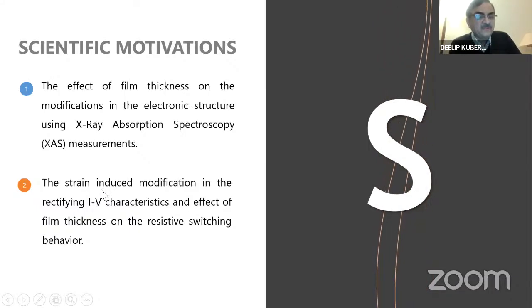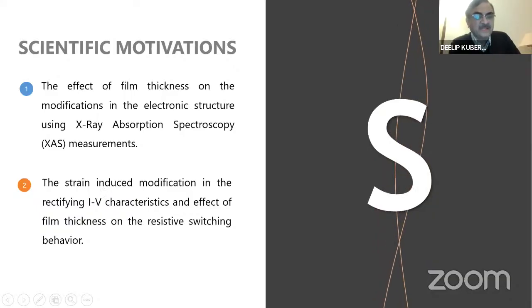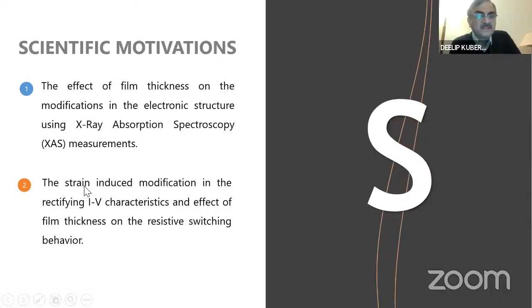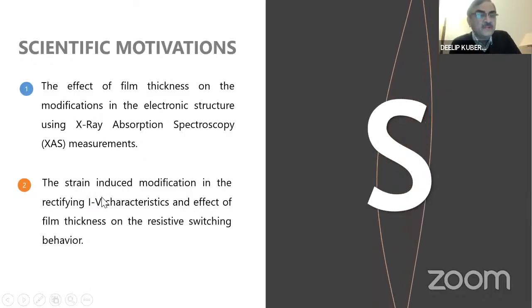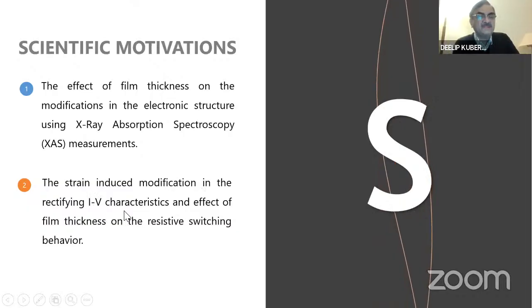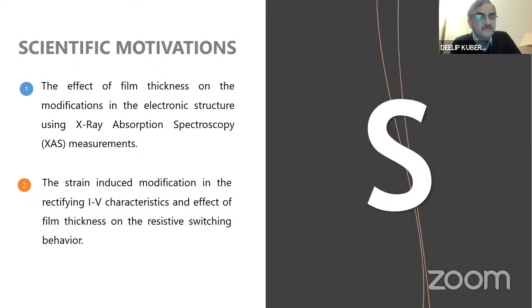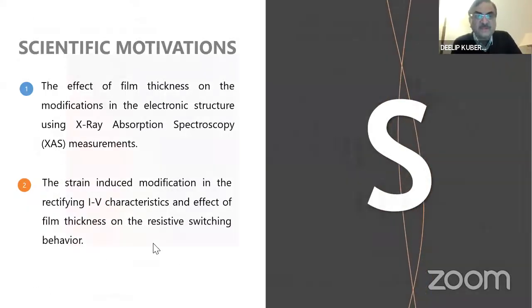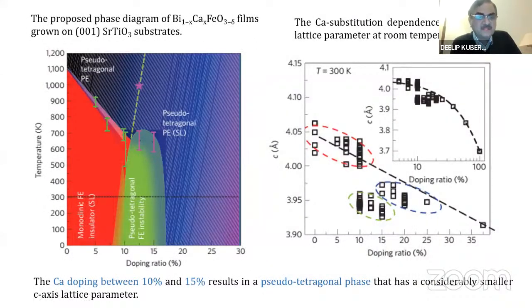And then, as I told you, one of the techniques to take care of the restrictions on the use of these materials is strain. So strain-induced modification, and their rectifying IV characteristics. These materials have a rectifying IV behavior, and there is the effect of film thickness on the resistive switching behavior. These were 2 modifications basically. These are the calcium doping between 10 to 15%. This was our study, and earlier some reports said that with 10 to 15% of calcium you get the pseudo tetragonal phase that has a considerably smaller C-axis lattice parameter.